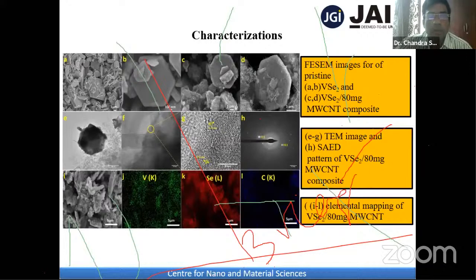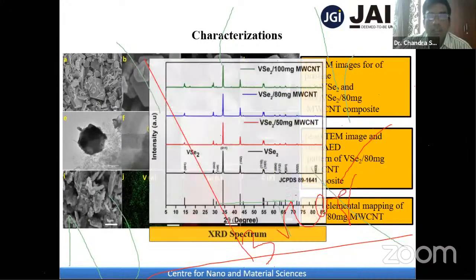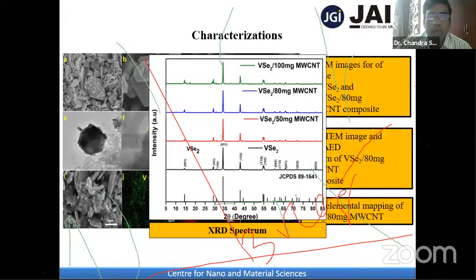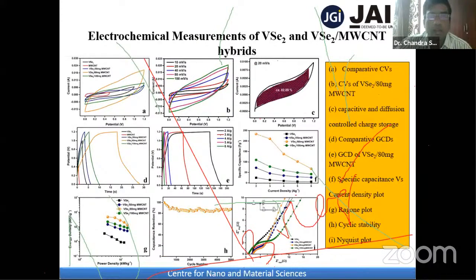You see this is vanadium diselenide with carbon nanotubes embedded. We do characterization using scanning electron microscope, transmission electron microscope, then elemental mapping. This is the XRD pattern, X-ray diffraction pattern, to characterize these materials. Then we do the supercapacitor performance. From this we come to know whether it is good or not.